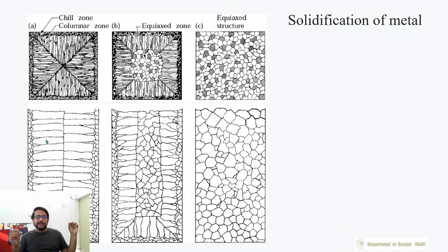However, as you go in, you will have these dendritic structures, these columnar structures of grains which will be towards the center, pointing towards the center. If the rate of cooling is much slower, then towards the center you will have this kind of a zone where the rate of cooling is very, very slow, and the grains get a lot of time to grow and rearrange themselves and remove any internal stresses because of the varied orientations they are in. And this is the equiaxed zone, and it is possible to get a completely equiaxed structure. An equiaxed structure will have more uniform, non-anisotropic material properties. So it is more desirable to have a homogeneous grain structure, but it's not always practical. However, it is possible to do it by using some additives and these kinds of processes, right?